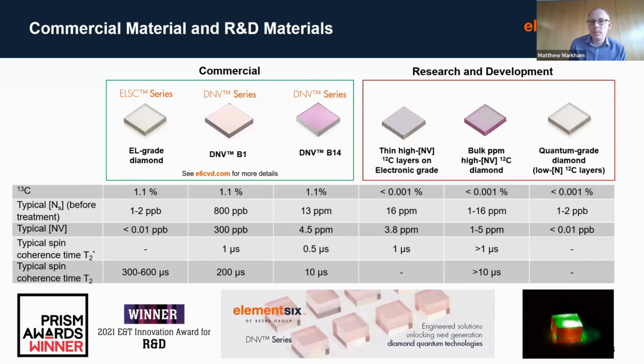But we don't just do these commercial materials. In my team, we do a lot of development work and produce another range of different materials. The first one here in the research and development box on the right, we have a material where we produce a very thin layer of NV containing diamond on top of one of our electronic grade diamonds. This allows you to do some of the imaging magnetic field sensing I spoke about earlier. And then in the middle we have another range of bulk diamonds containing a range of different nitrogen concentrations. And then on the far right, we have a carbon-12 high purity material. It's akin to the electronic grade diamond, but this time we've removed the carbon-13 you get in the material, and this improves the spin decoherence time. So if you go to the next slide.